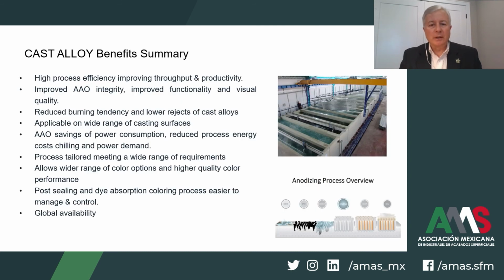So in summary, traditionally anodized oxides for cast alloys require longer anodizing process times for producing inadequate layer quality, but the cast alloy process allows for normal production throughput. Additionally, capitalizing on the realized savings of power consumption, reduced energy costs with chilling and other things that we weren't able to discuss during the webinar today. Higher anodizing voltages normally required for cast alloys have much less burning tendency with the process, resulting in less rework, improved layer integrity, and overall increased productivity. Post-sealing and dye absorption coloring processes are easier to manage and control.